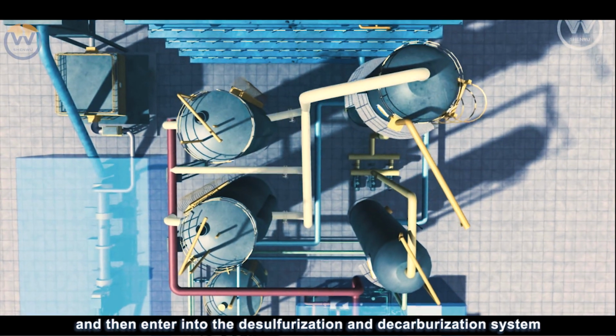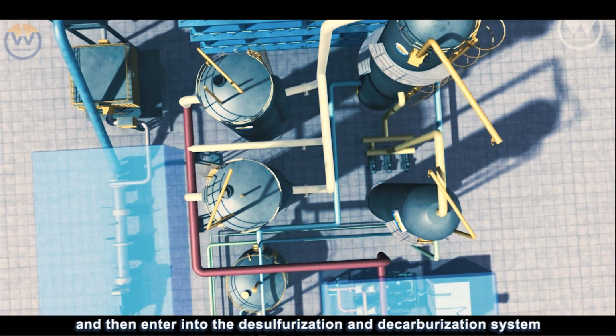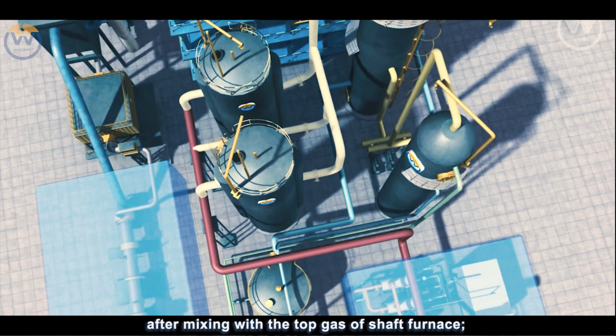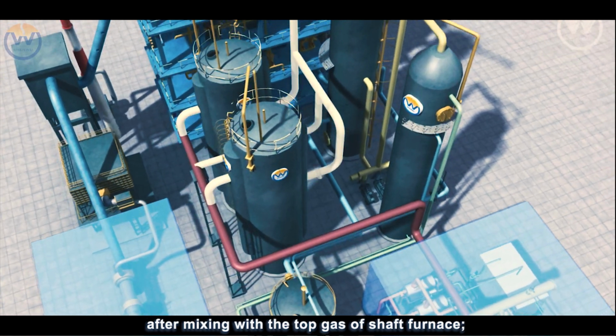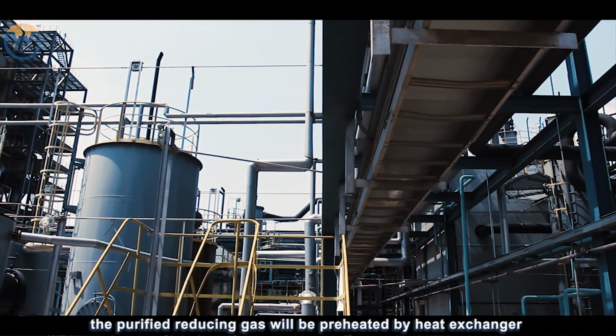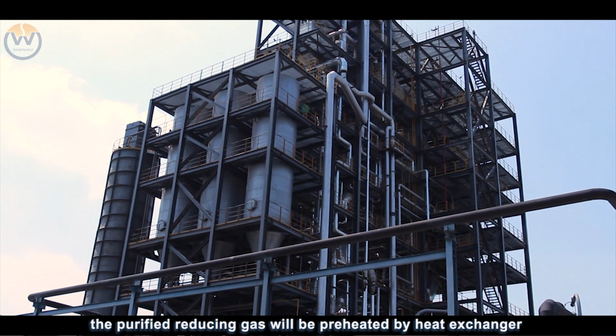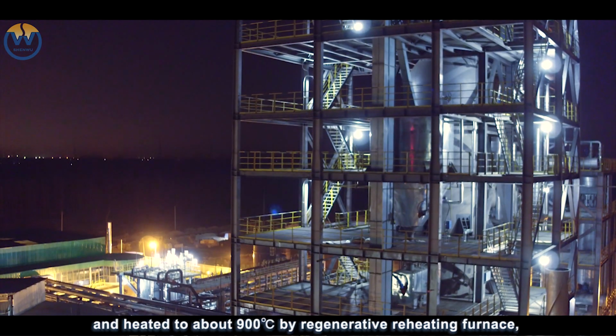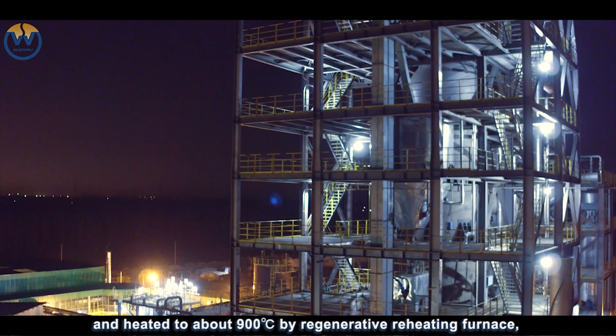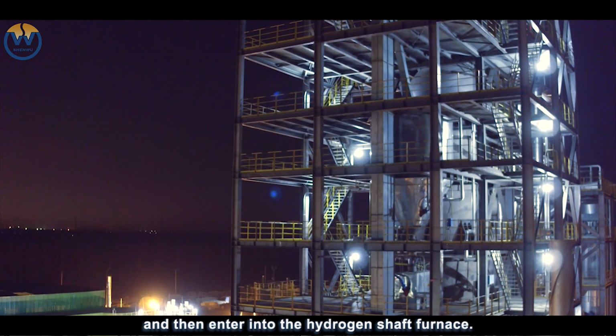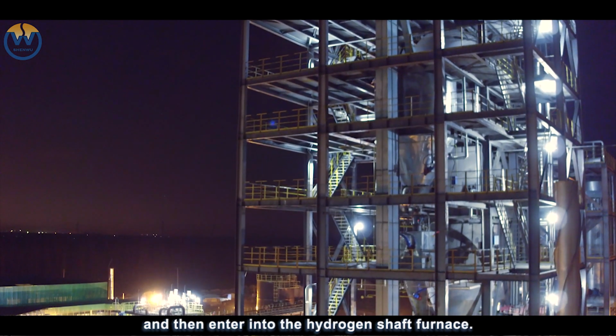and then enter into the desulfurization and decarburization system after mixing with the top gas of shaft furnace. The purified reducing gas will be preheated by heat exchanger and heated to about 900 degrees centigrade by regenerative reheating furnace, and then enter into the hydrogen shaft furnace.